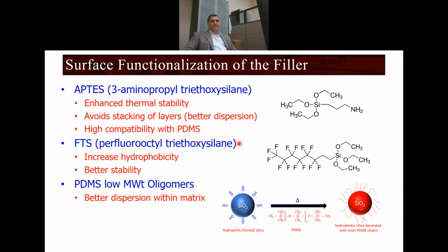Another treatment is to increase the hydrophobicity of the silica itself before you put it into the matrix, using a fluoro chain. So you hook this side to the silica as a nanoparticle, and this chain will be dangling. This is an effort to increase hydrophobicity and hopefully get better stability. Also, another strategy is to functionalize the silica itself with low molecular weight oligomers. The silica has plenty of OH groups, so we are trying to hook a PDMS chain from one side to this silica. In that case, you get much better dispersion of the silica within the PDMS matrix.